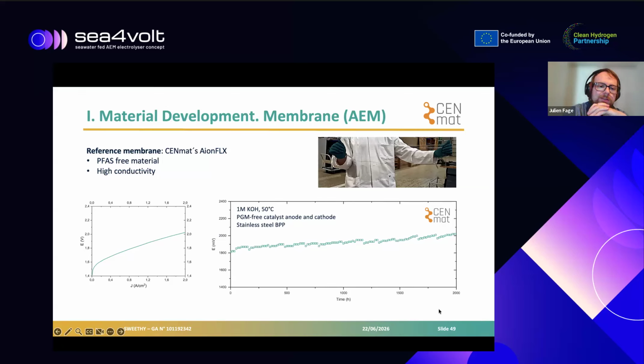Our developed membrane is called AionFLX. So it's a PFAS-free material with high conductivity. You can see that it's giving about 2 volts at 2 amps per square centimeter in 1 molar KOH at 50 degrees using our own PGM-free catalyst for the anode and cathode. And here we are using a stainless steel bipolar plate. The standard test is running 2000 hours with degradation matching or actually way below the target of the project. But here I will show only tests in 1 molar KOH, so we don't have seawater. We are first testing the membrane alone to confirm its stability, and then we'll move on to seawater with our partner at CNR in Italy.